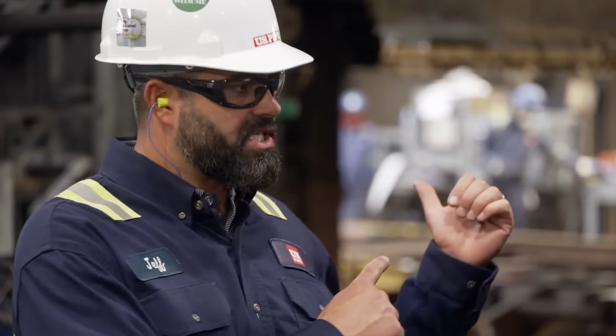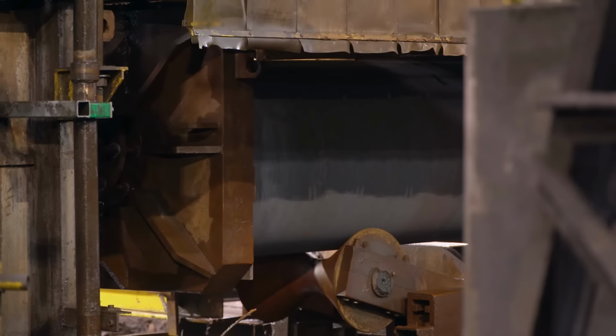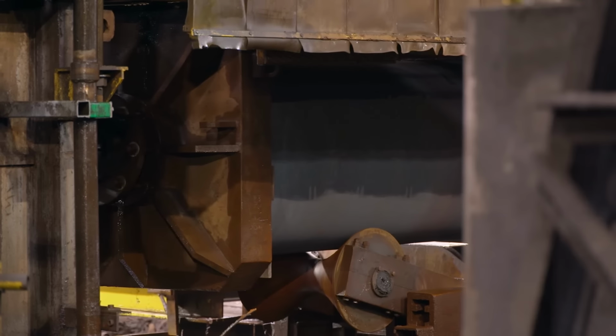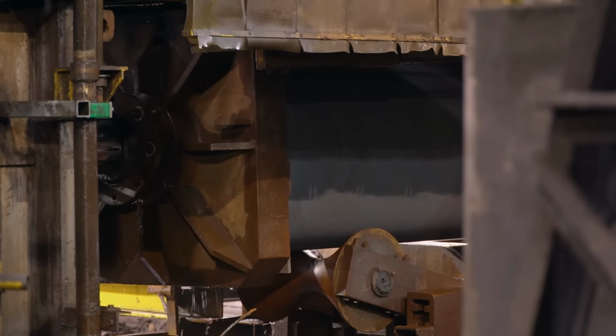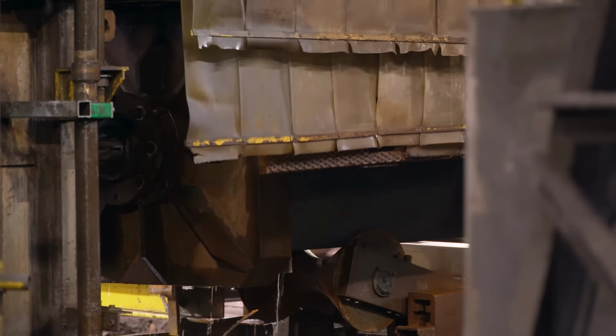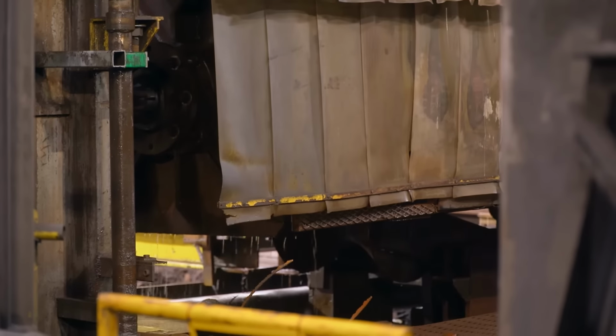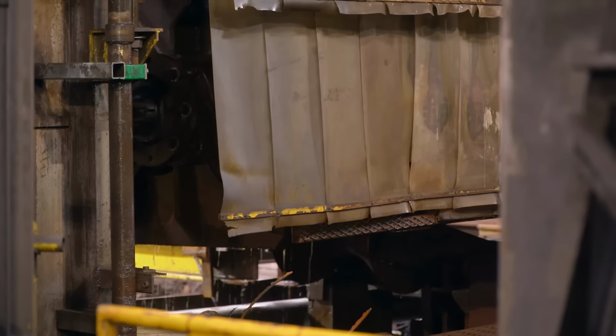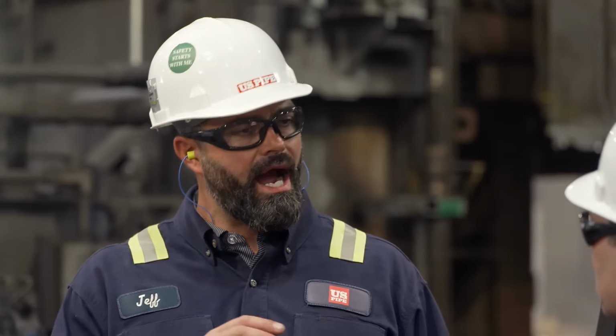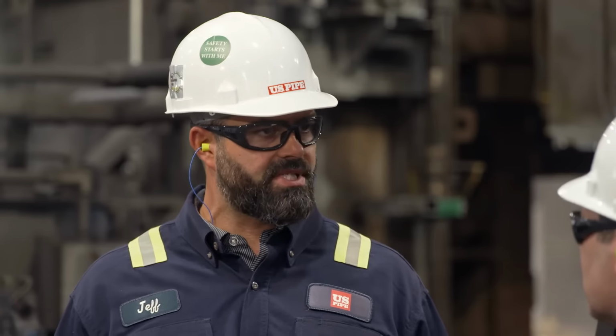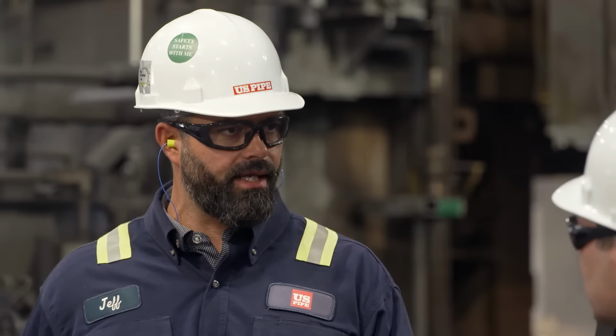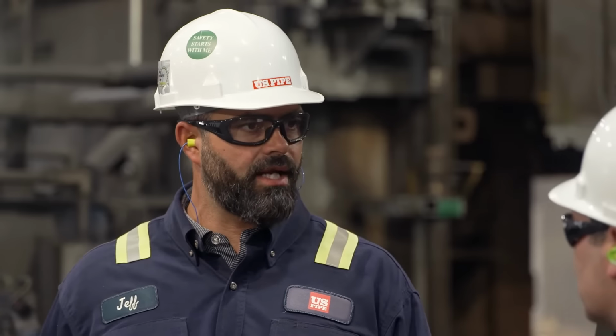So this is the first step. It's a hydrostatic pressure test. We take it to 500 PSI. It's all or nothing. If that pipe is ductile, it'll pass. But if it's not ductile, it'll fracture, and out to the scrapyard it goes. After that, we start testing the iron itself, making sure it meets the standards we say it does, and then it goes to cement lining. So we're going to go check out cement lining. Let's go.